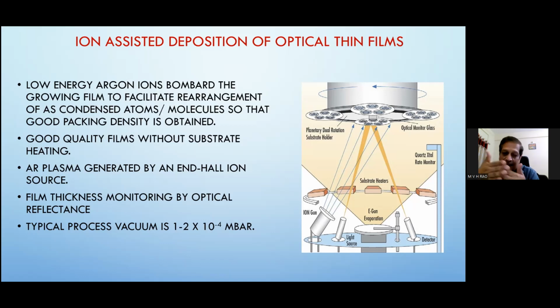re-etches the film. It's a growing film, but it is partially etched by this ion gun, so that all the high-point islands are etched and it becomes smooth. And then the atoms are once again rearranged. You are giving certain energy to the atoms to get themselves rearranged, so that the film grows in a much smoother way. So ion assist deposited films are much smoother.